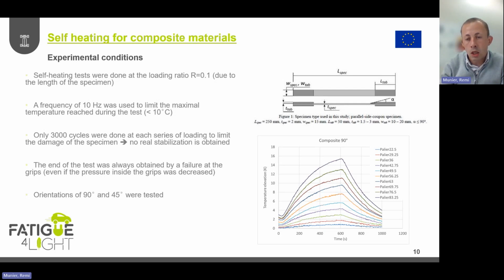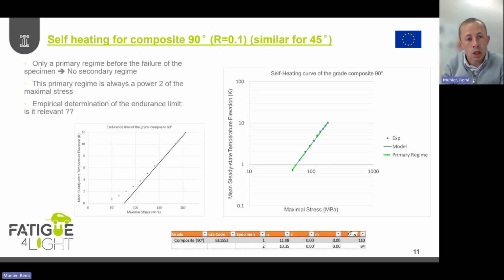There was a need to change a bit the conditions for the test, to reduce the frequency, just to be able to not overheat the specimen. We also needed to reduce the number of cycles to reduce the damage on the same specimens, but then we were able to obtain one self-heating curve, which is quite strange here for the results.